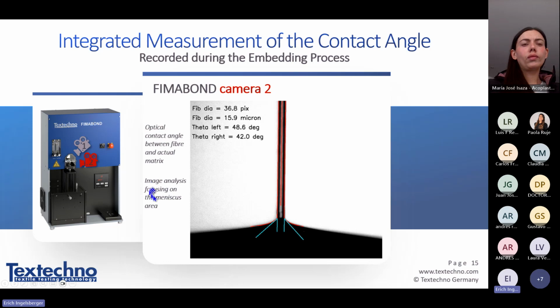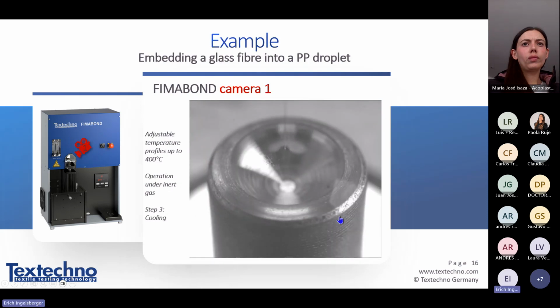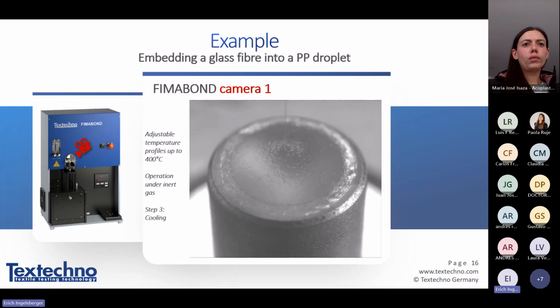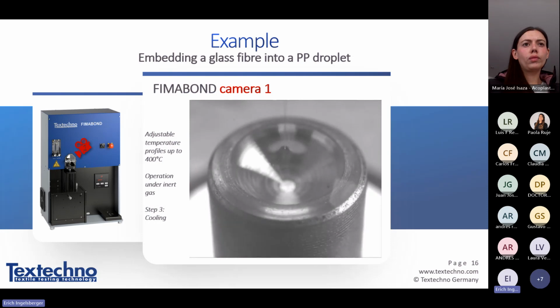Here the image analysis is focusing exactly on the point where the fiber touches the matrix drop. Last step, in this case of polypropylene, is of course the hardening or cooling down. You can see by the surface that now the droplet cools down. And then the specimen is ready for testing.